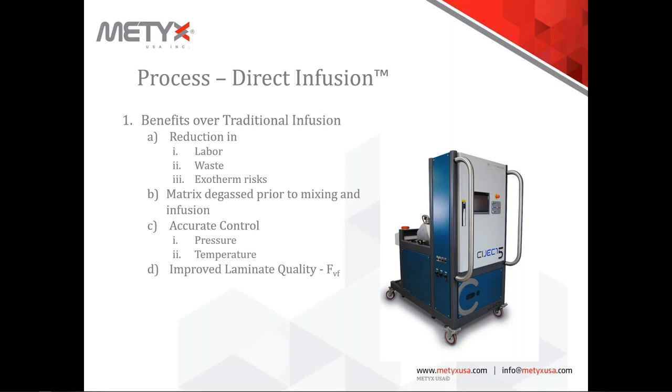You're optimizing the fiber ratios to whatever that particular architecture can handle. Some fiber ratios are 65% based on a quadrax. Some are 72% based on a triax. And again, it depends on the architecture of your fabric, the permeability of your laminate and so forth, of what you're going to get. But this single point control allows you that flexibility to monitor that process and to give you the quality assurance. And more importantly, it's a repeatable process.